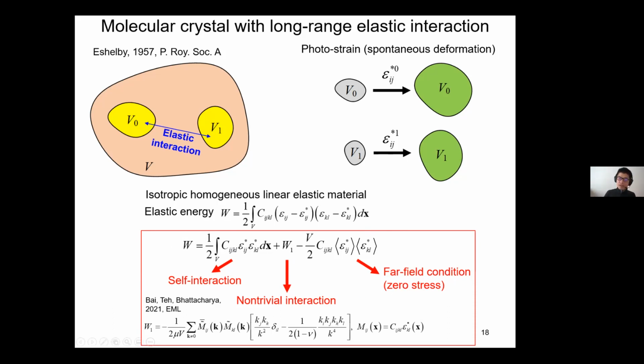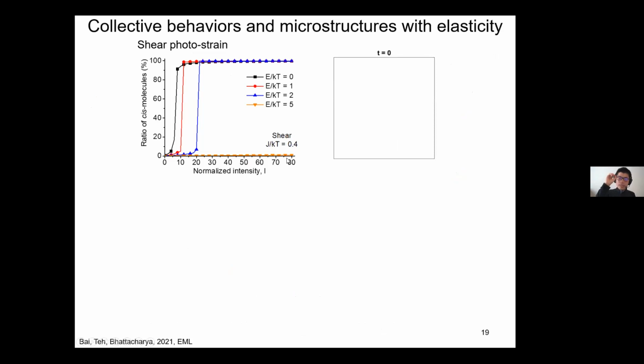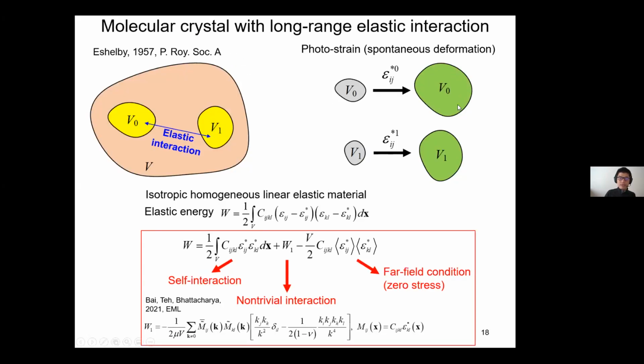If you take a look at this carefully, this is really a dipole-dipole-like interaction, but just in a higher order tensor form. So the interaction here is really dipole-dipole, and we know that dipolar interaction is a long-range interaction. Okay, so this is something interesting. What we did is we embed this model into this Monte Carlo Ising model, and this is the result. So I have a shear photostrain. Basically, if I have a strain here, the strain is a simple shear.